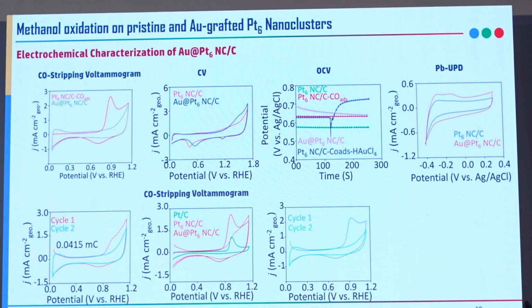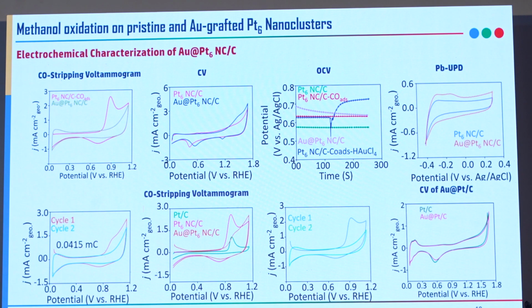While we are checking the CO stripping voltammetry, you can see the CO peak is reduced. It is broadened. That means only some of the platinum atoms are available for the CO. But you can see there is an anomalous, unique behavior on the Au decorated one. Along with the CO stripping voltammetry, we could find a hydrogen desorption peak also. That means platinums are available for CO stripping and also for this hydrogen. But unfortunately, we couldn't decorate any Au atoms on the surface of this commercial Pt/C.